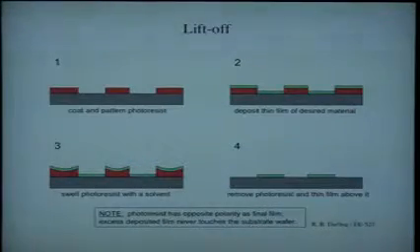The other way of doing is exactly the opposite, wherein you have initially the photoresist itself pattern on a plain glass. Having done that, now you bring in gold on top. You can see gold is getting coated here as well as directly on the glass itself. And then you swell the photoresist with a little bit of, you can put it in the solvent where the photoresist can dissolve. You can see that the metal is being now lifted out. And then only in these regions where it got to see the substrate, it stays on. The rest of the regions, along with the photoresist, metal also goes away during the development step. So that's how you make metal patterns.